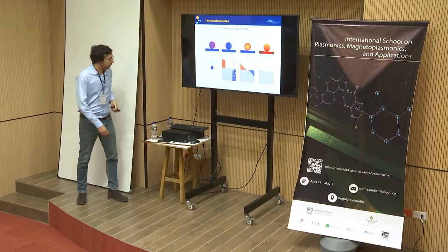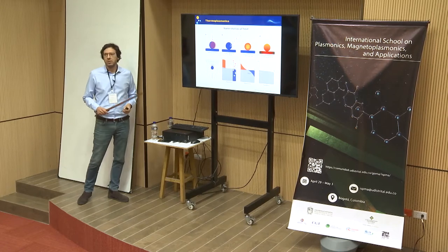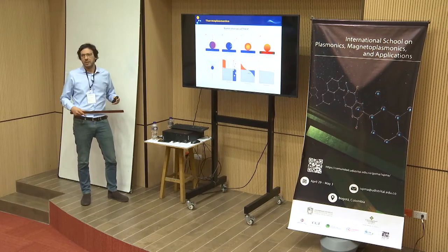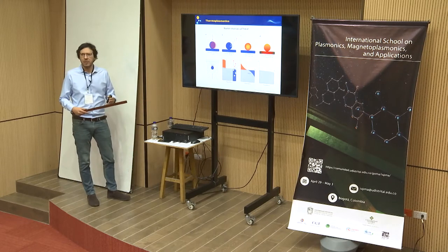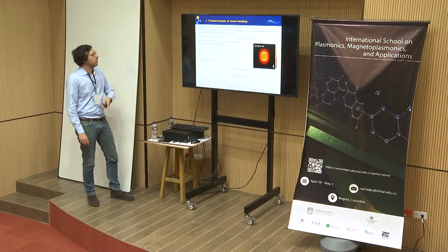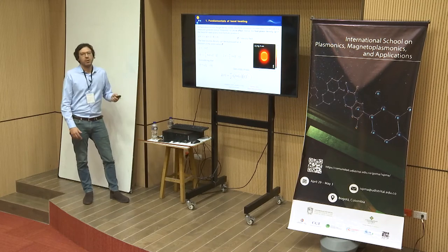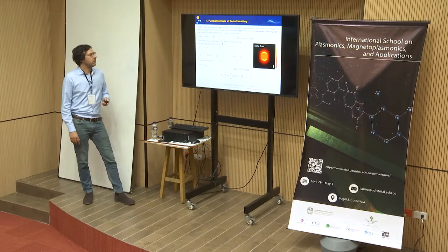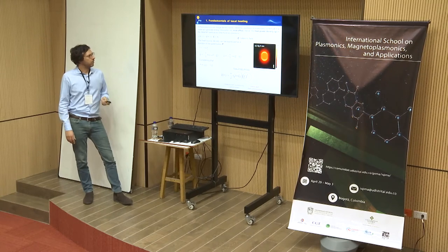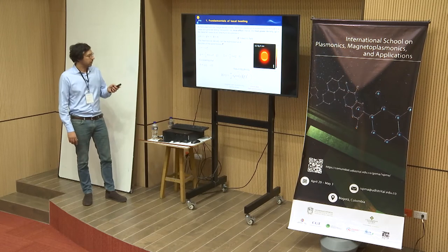So this is again the time evolution of the surface plasmon excitation. After the excitation of the plasmons, we have the dephasing of the plasmons, and then in a time of 100 picoseconds to nanoseconds, all the energy stored in the resonant excitations is dissipated into the lattice of the material. And so we can create really intense temperature at the nanoscale. This heat simply comes from the Joule effect, from the dissipation of the energy due to the electron scattering into the surface plasmon oscillations, and therefore the heat source density can be easily obtained considering the Joule effect.